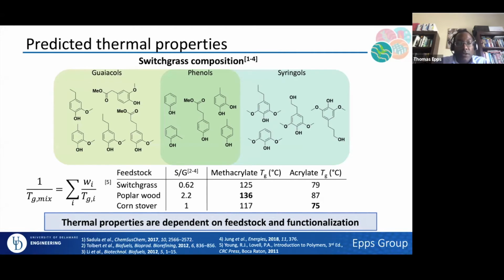So one of the things that's quite nice here is that if we have information on the composition, which in these particular cases that I'm showing in the table, we can actually get from the renewable feedstock library at Idaho National Lab. But the key point is, if we know the composition of different guaiacols, phenols, and syringols, because we've got that glass transition temperature data, and because we also have statistical or random copolymerizations or heteropolymerizations, we can actually predict what glass transition temperatures we would get if we made polymers from switchgrass, poplar wood, corn stover, used coffee grounds, other sorts of material, peanut shells, for example, and whether it's methacrylated or acrylated, and all of these values are within 5 degrees of what we've gotten when we do the experimental complements as well.